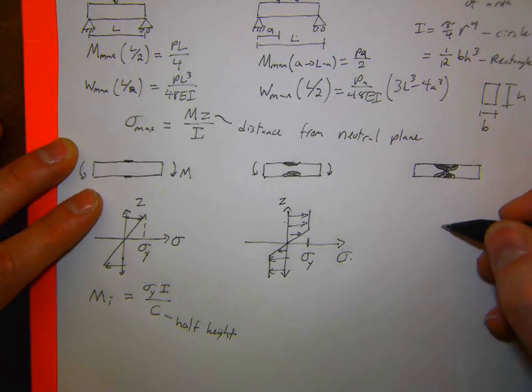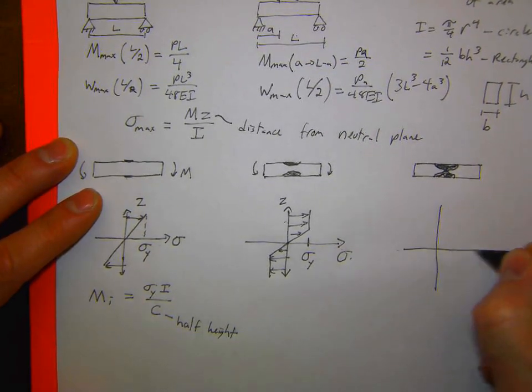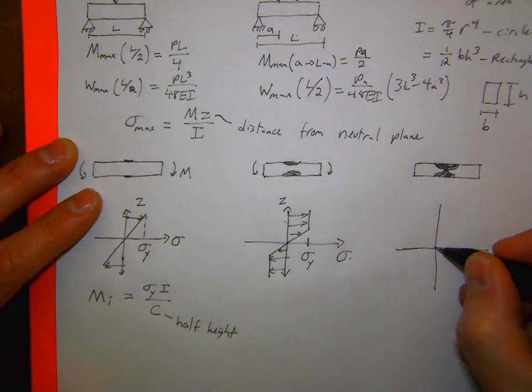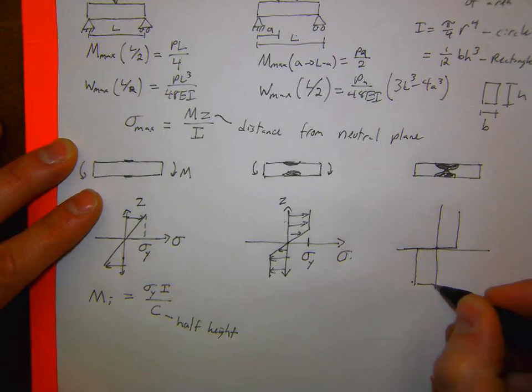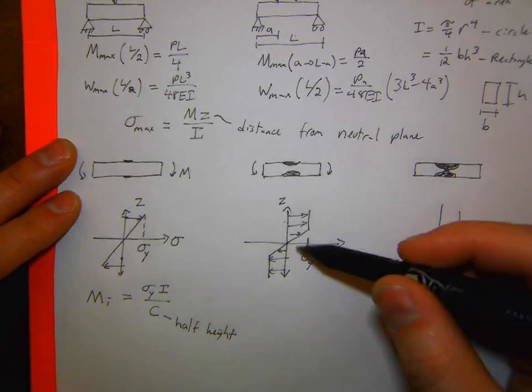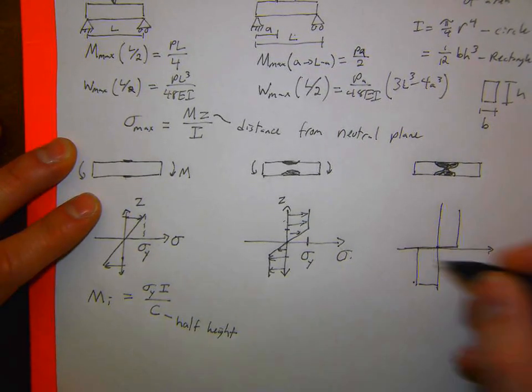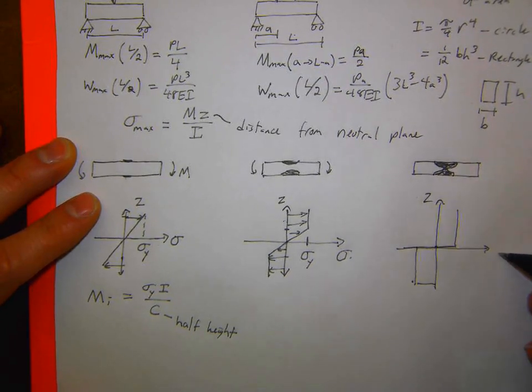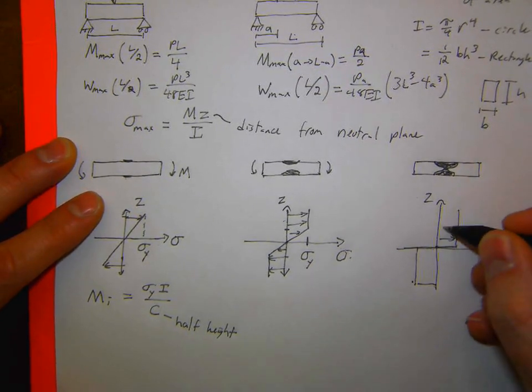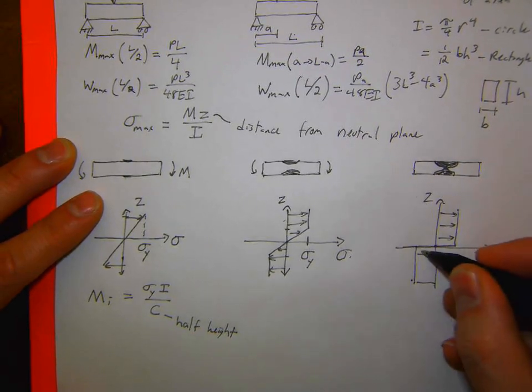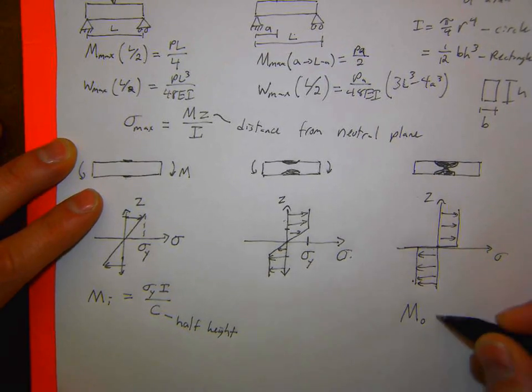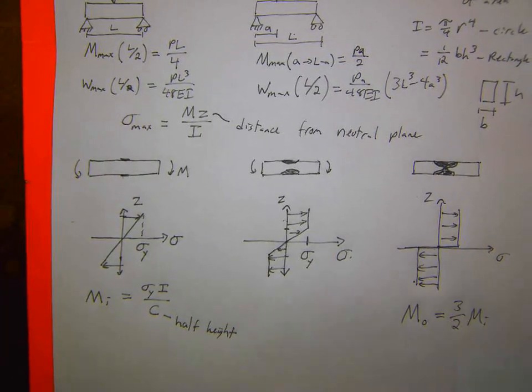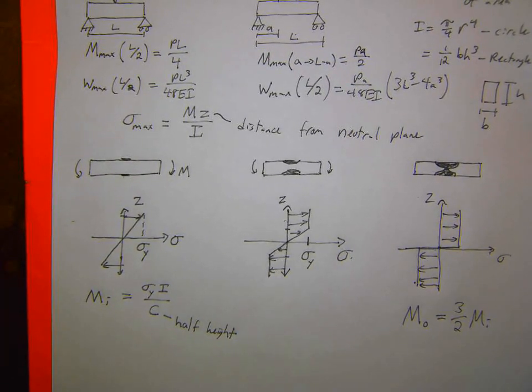The moment distribution for an elastic, perfectly plastic beam — which is the only case you need to know — eventually forms a plastic hinge where the plastic region touches in the middle, meaning the whole beam is deforming plastically through the center. At that point, we assume a flat stress profile, where the distance from the neutral plane to the yield point is approximately zero. That happens at M₀ = (3/2) × M_I.